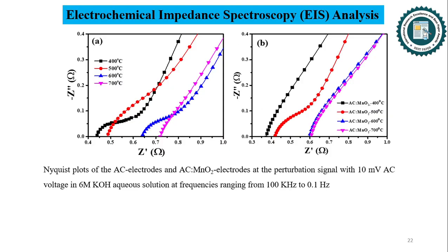Now I'm moving on to electrochemical impedance spectroscopy, which is EIS, also called EIS measurements. So EIS measurements were conducted on activated carbon and hybrid composite electrodes in a 6 molar KOH solution across a frequency range of 100 kHz to 0.1 Hz, generating Nyquist plots. These plots revealed polarization resistance at high frequencies and capacitive behavior at low frequencies.